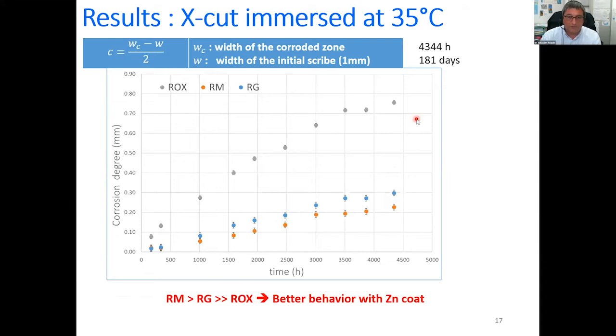Now, these are the results for the X-cut panels that were immersed at 35 degrees C in the sodium chloride solution. So this is the corrosion degree, plotted versus the time of immersion. As you can see here, finally the ROX system, so only the organic coatings applied onto the steel, shows the highest value of the corrosion degree. So finally, the worst adhesion to the substrate.